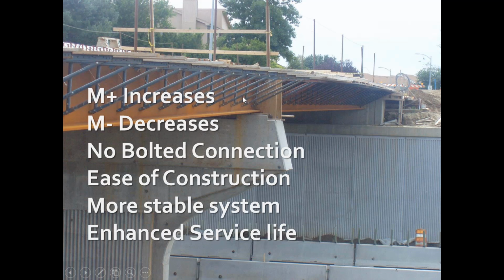Also, service life. We have many problems with the steel girder bridges at the supports because of the water, moisture getting from the top, from the joints, from the expansion joints and so on, and causing a corrosion at the end of the steel girders. In this case, the end of the steel girders are secured against the moisture by being casted inside the concrete. And that helps a lot. So this detail helps the service life.